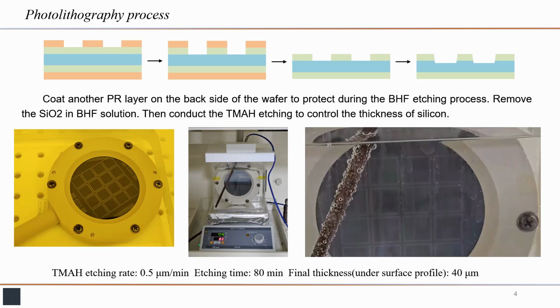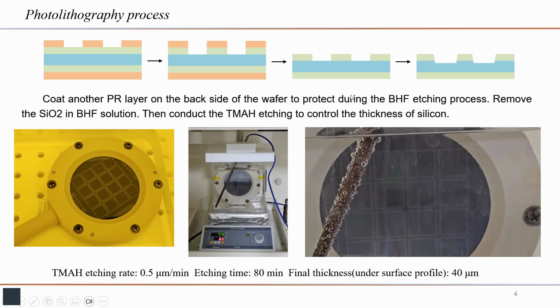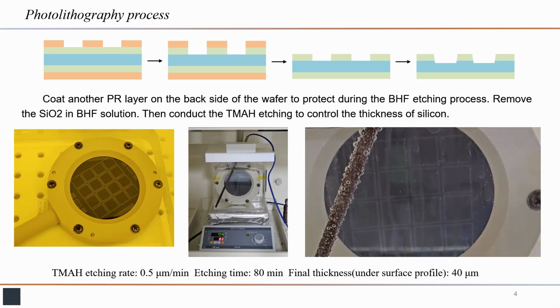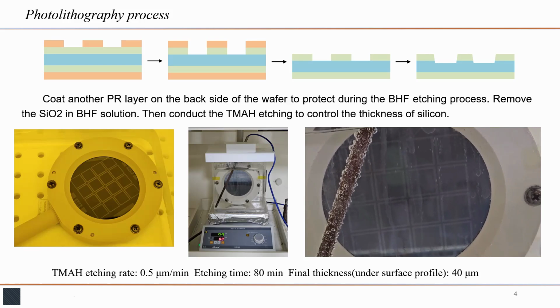As you can see, the temperature of the solution we used is 80 degrees. And this video is just showing the bubbles generated when conducting the TMAH etching process. The TMAH etching rate is 0.5 micrometers per minute, and our expected thickness of the final diaphragm is 40 micrometers. So we took the etching time as 80 minutes. And finally, we have checked the thickness and the surface profile.